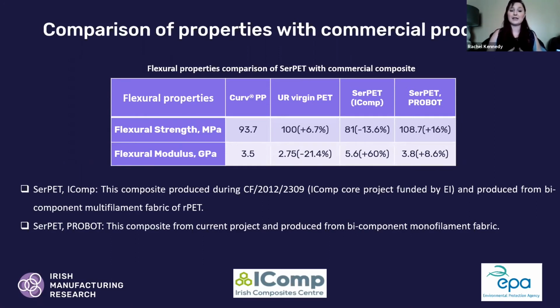But this was done with material from different suppliers. We had a different manufacturer. So we're going to focus on the Serpet PROBOT one, which is the one that we made during this project. And this is better in both of the properties. We have an increase of 16% in strength and 8.6% in modulus. This improvement is also better than your unreinforced, which is why we like to do composites.